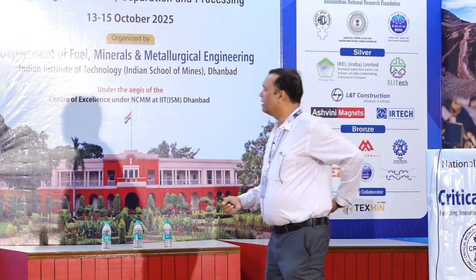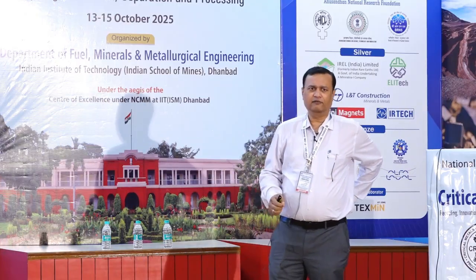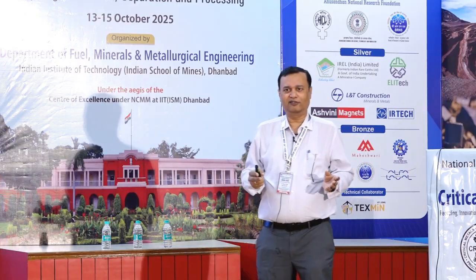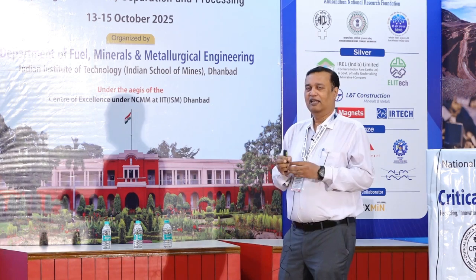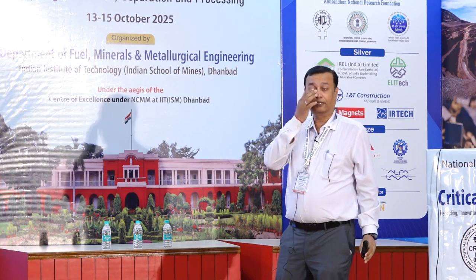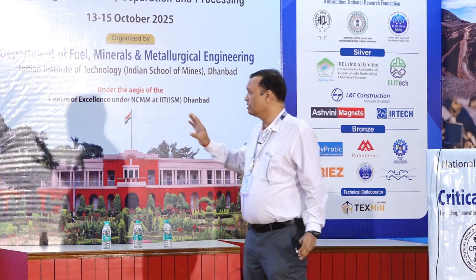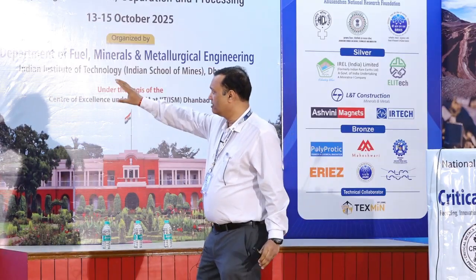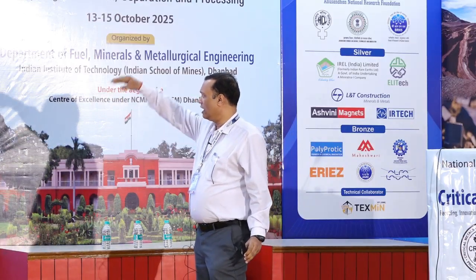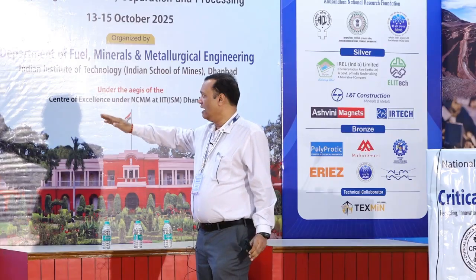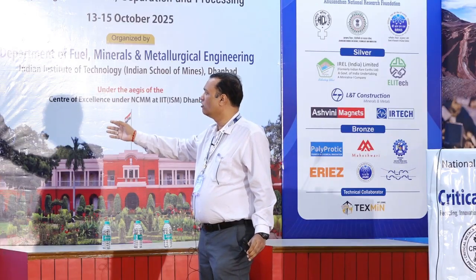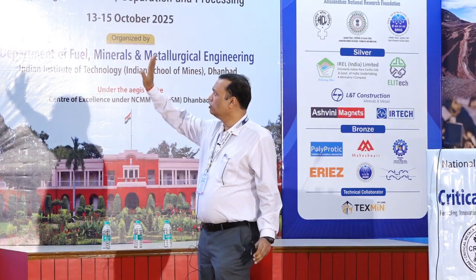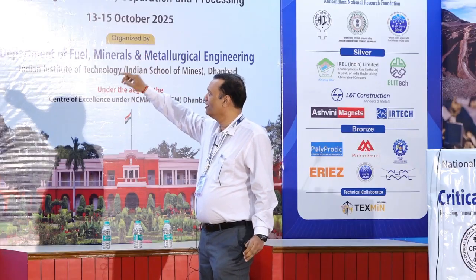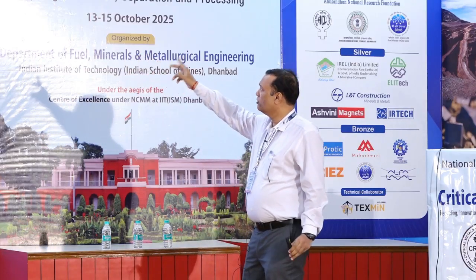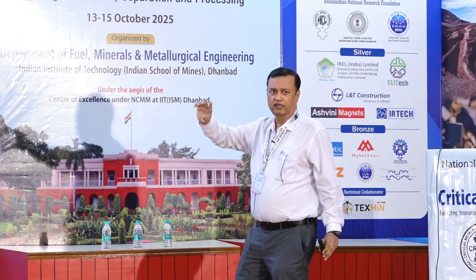Coming to 2:17 magnets, this magnet has a very complex metallurgical microstructure, and this microstructure is developed after 5 days of heat treatment, where we see that it forms a cellular microstructure in which the cells are basically the 2:17 phase and the cell boundaries are the 1:5 phase. And there is a redistribution of iron and copper in 2:17. If you see, 2:17 contains iron, copper and zirconium, where copper and zirconium are added to increase the coercivity and iron to increase the Br.